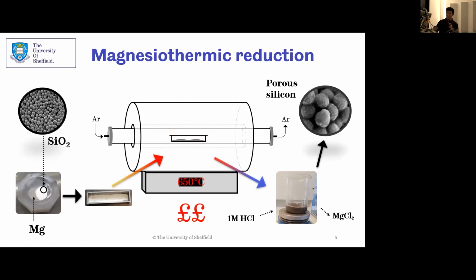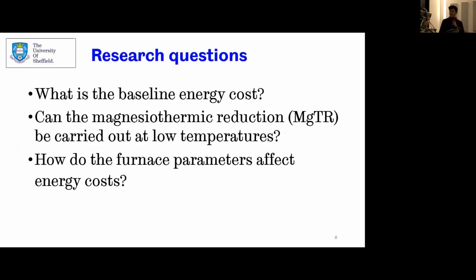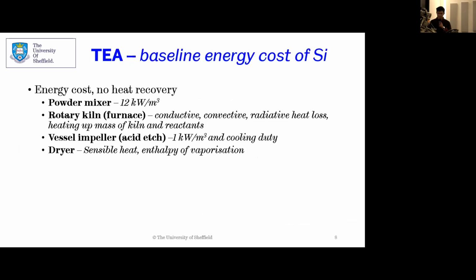So the issue here is that 650, as I will show you, is quite an uneconomical temperature. The baseline energy cost at the moment hasn't been calculated or forecasted, and therefore, can the magnesium reduction be carried out at a lower temperature than 650? In fact, I'm going to give a spoiler here. Yes, it can, and I'll show you how. Because it can be carried out at low temperatures, how does this affect the economics of the process? So how much does it cost to do it at 650 versus the low temperature? For the first question, I assigned common industrial equipment.